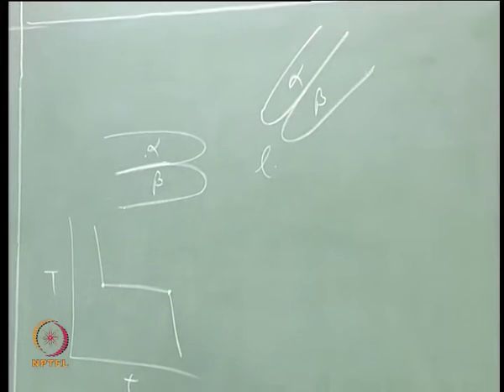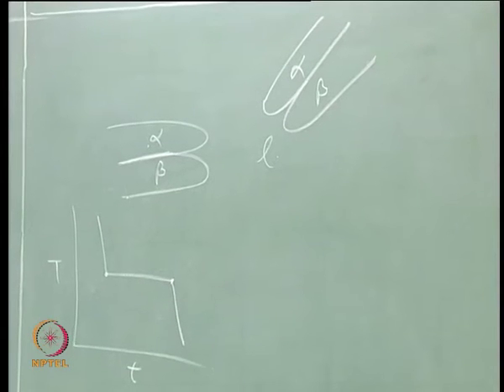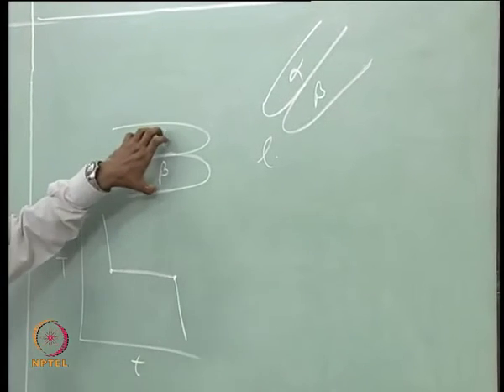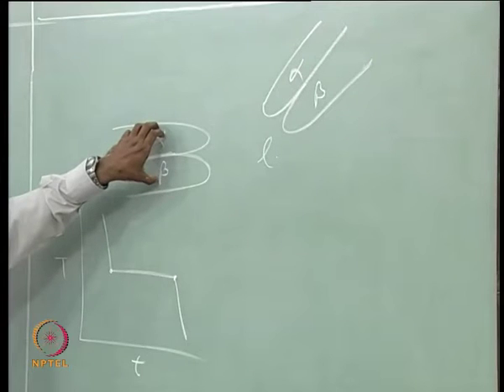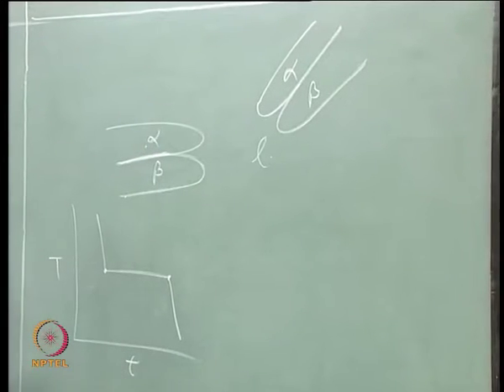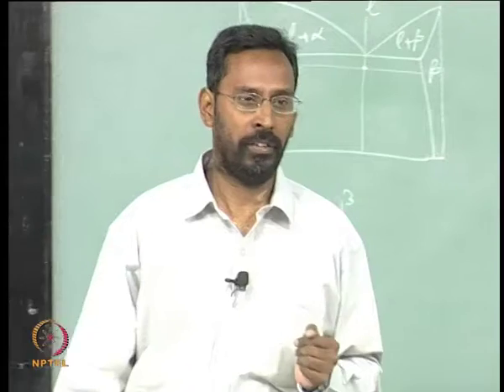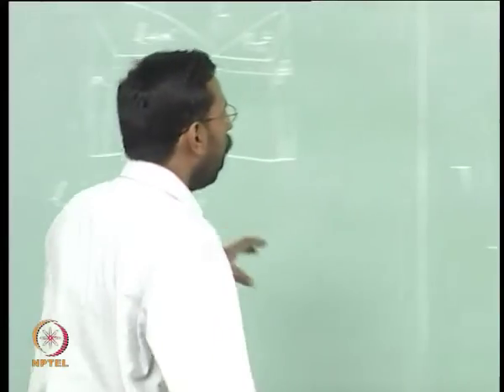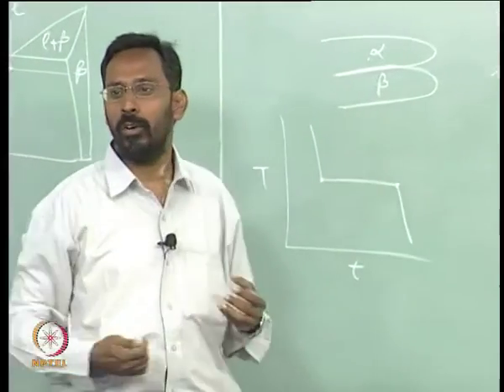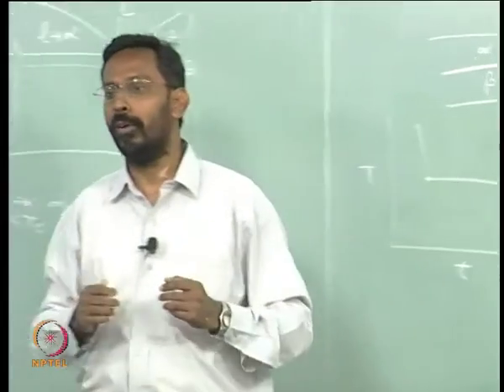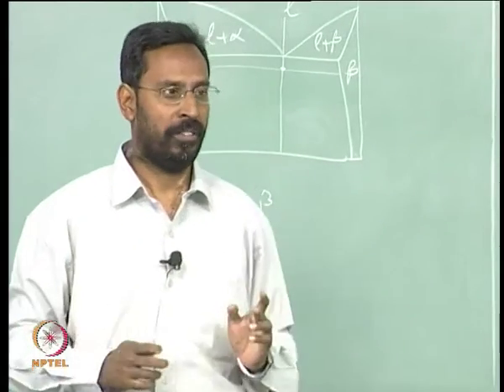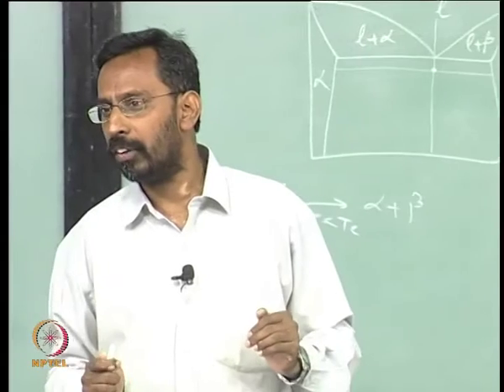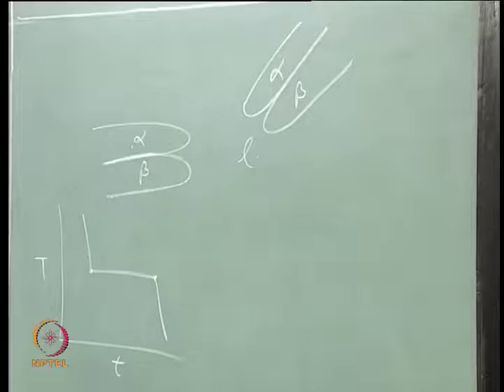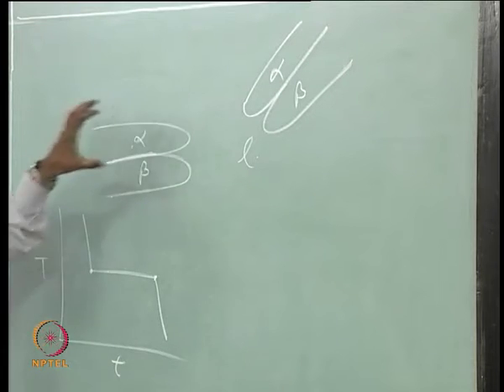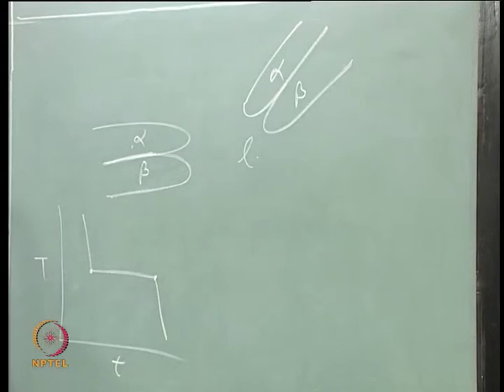So there is a name, because this is called a eutectic colony, and what you get are called colony boundaries, eutectic colony boundaries. So you have a number of such eutectic colonies grow, and you will have eutectic colony boundaries coming in like grain boundaries. They are analogous to grain boundaries, and you would see in most of such eutectic microstructures boundaries of different alpha beta growing in different orientations.